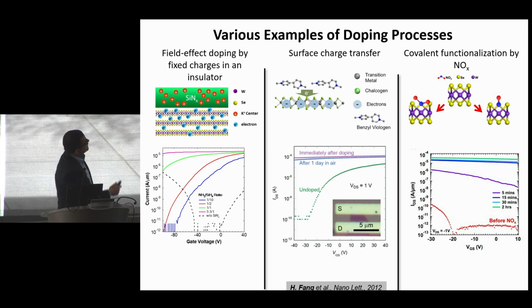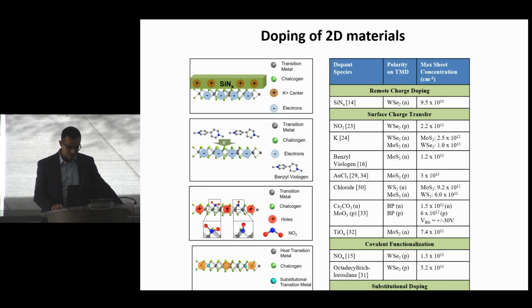Another method would be to do covalent functionalization, and in this case, we looked at forming oxynitrides, and you could just do plasma reaction or low temperature reaction with NO2, and you can form oxynitride. And what happens is you form tungsten oxynitride on the surface, and tungsten oxynitride has a high work function, so that's how you get surface charge transfer. So this is just a library of different doping techniques.